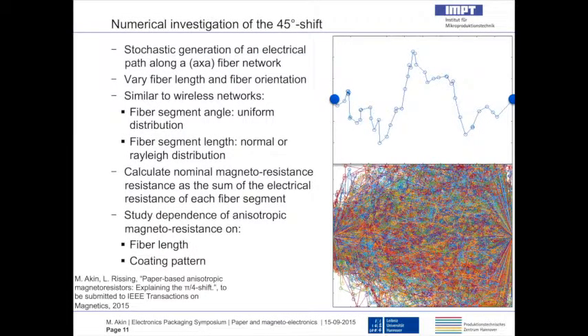So in order to back up that result, we implemented a numerical model. In this model, we generate a statistical distribution of fiber paths between 2 points where we vary the fiber length and the fiber orientations in a square surface, an A by A surface. The width is A, and we measure the resistance along that path, assuming that the magnetic field is in the horizontal direction, and we look at the magnetoresistance of that entire path as the sum of the magnetoresistance of each of those segments that you see, each of those 2-point segments that are connected with each other.